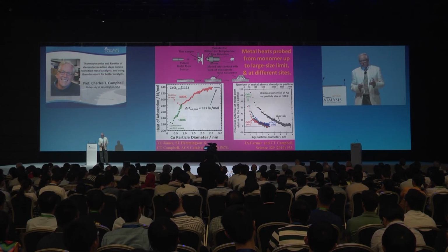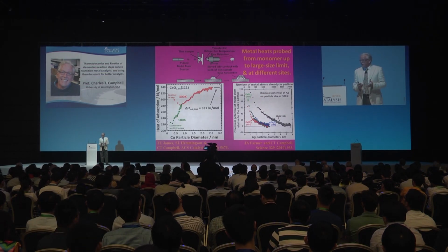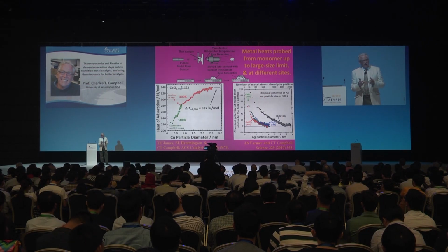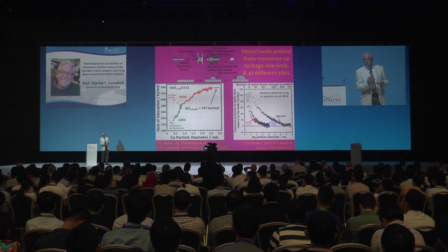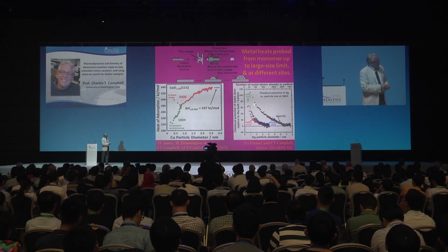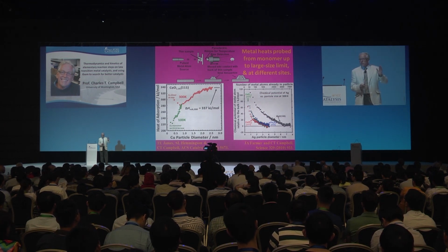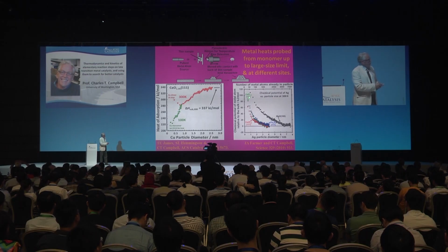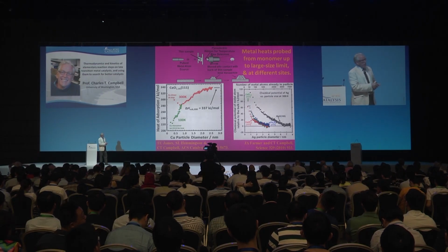The more I've worked with this type of data, the more I realize how clever Gibbs was with the name chemical potential. It really describes the potential that a species has to do chemistry. And the higher in chemical potential, the more aggressive the species is. And really, going up this hill is like moving to the left in the periodic table. And I think this is one of the reasons why small nanoparticles of gold can do catalysis that's more like something a little bit left in the periodic table. It's no longer as inert because the metal atoms in small particles have high chemical potential. They're more aggressive in their chemistry.